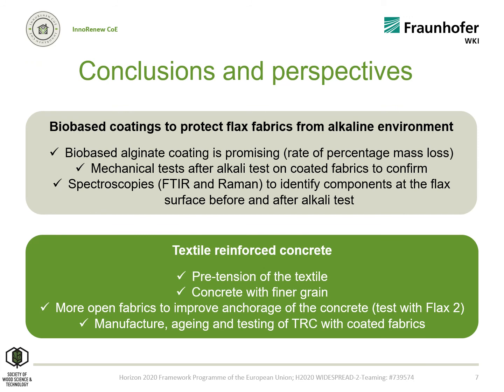To conclude, we found the bio-based alginate coating to be promising. Some spectroscopy analysis will help to identify the components that are removed by the alkali test. The experimental settings for the manufacturing of the textile reinforced concrete need to be improved by using pretension of the textile and either using concrete with finer grain or a more open fabric like the flax 2 grid.